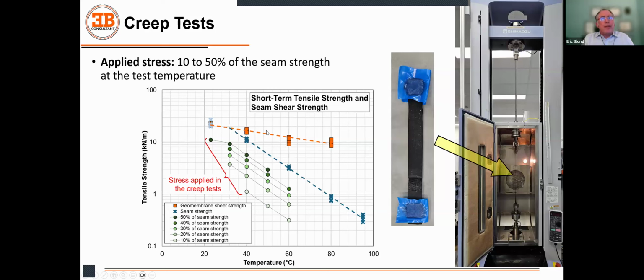And so you can see here the orange graph is the tensile properties of the sheet. The blue line here is the seam. So we used a variety of temperatures and percentage of the seam strength. So in dark green, it's 50% down to 10%. And we've looked at how that would affect the behavior of the seam.